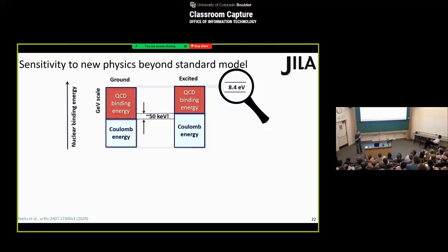But from the geometrical model, we can calculate that the Coulomb energy difference between the excited and ground state is actually about 50 kilo electron volt. So now, if the fine structure constant alpha is changing slightly, this would change the nuclear transition energy proportional to the 50 keV Coulomb energy difference. So we get a very large enhancement in sensitivity to fine structure alpha variation over time by monitoring our nuclear transition. And this enhancement factor is about 6,000.